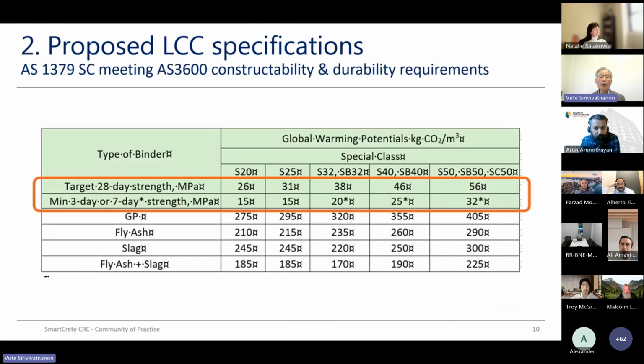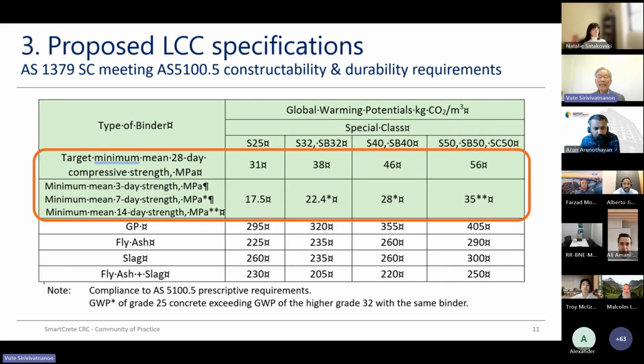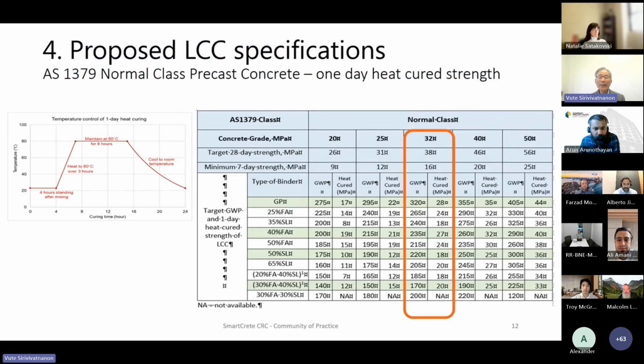Very quickly, the second group is that of special class concrete. The special class is represented by S, and same thing, there are requirements for 3 and 7 day according to the construction requirement of 3600. Whereas if you go for the next one, this special class concrete also meets all the requirements in 5100.5, with 3-day strength, 7-day strength, and 14-day strength, depending on which grade and the range of embodied carbon that you can ask for. The fourth group is an attempt to give precast a bit of information. For a particular curing regime that I show on the top left-hand side, the early one-day strength that you can expect from those different normal class concretes is given there for precasters.